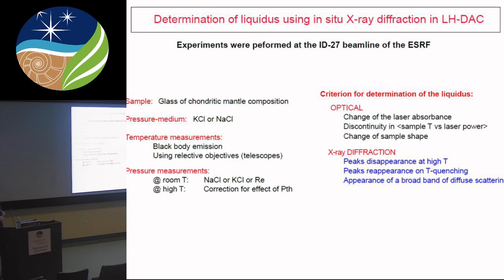We use salt as pressure medium. They may not be excellent, but they are very refractory at high pressure, so it's very convenient for our system. We could use argon. We tried several times. It's not very different. Temperature is measured classically using the black body emission or gray body emission, but we have used for many years now reflective objectives, which prevent chromatic aberration. It's very useful in our opinion, especially on a beamline where the position of the sample is dictated by the X-rays, not detected by the optical system. So it prevents problems in the temperature measurements.